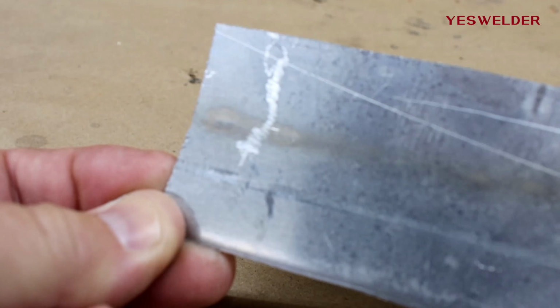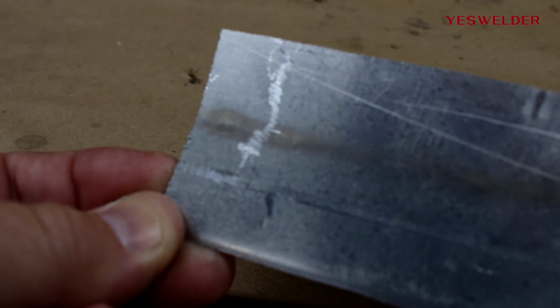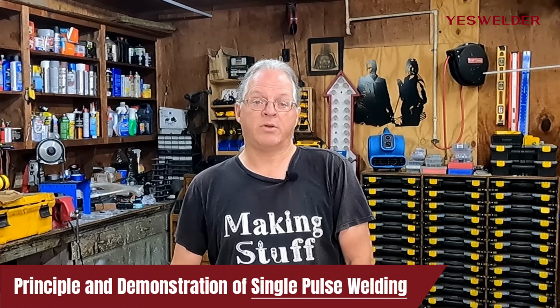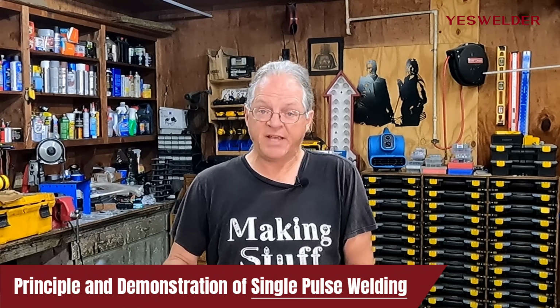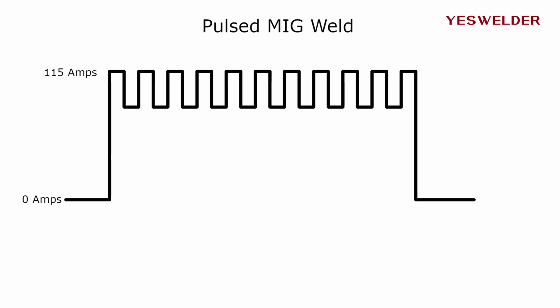The weld did get more penetration, but if we look on the bottom, you can see the heat was starting to soak through. So this is where pulse MIG welding comes into play. It's just a modified form of spray transfer that combines the best of both short circuit and spray transfer methods. Pulse welding, also known as single pulse welding, achieves this by adding a pulse to the current.